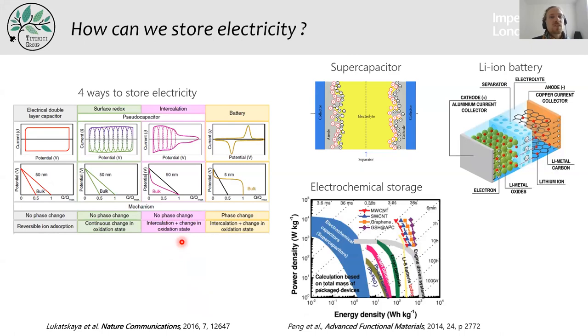So there are several ways we can store electricity. Here are four examples. On the extreme left, you have the electrical double layer capacitors, and on the extreme right, you have the batteries. Here on the first line, you can see what we call the electrochemical signature. These are cyclic voltammograms. It means that when you are charging your device, you have your positive terminal and negative terminal, anode or cathode. And when you are controlling the potential and recording the current, this is called a cyclic voltammogram. The cyclic voltammogram of a supercapacitor is square or rectangular like this. And the cyclic voltammogram of a battery has these massive redox peaks here.